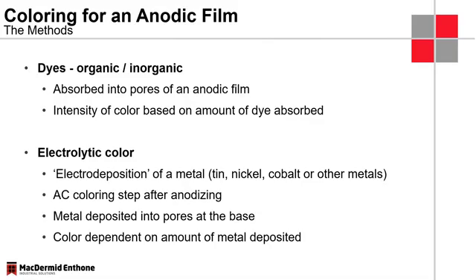So let's move on to the coloring of the anodic film. There are really two ways of doing this. One is using the traditional dyes as an immersion dye. These can be organic or inorganic, and these dye particles are absorbed in the pores of the anodizing layer through just immersion. And the intensity and the depth of the color really depends on the thickness we apply to the aluminum part, obviously the concentration of the dye itself, the temperature, and in general the activity of the anodizing dye.